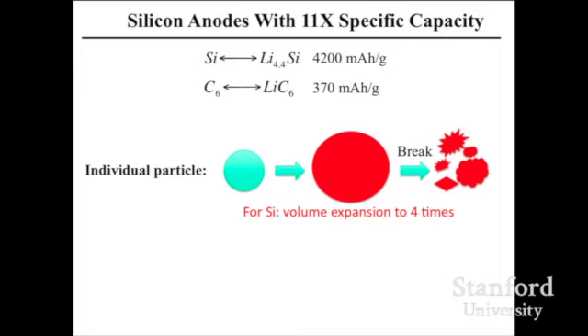This lithium comes in, breaks all the silicon-silicon bonding, and we form lithium-silicon bonding. Their volume expands very big, 400%, and then a lot of stress builds up, and they break. And this breaking is really killing the battery. The first time you charge your battery, the battery is already dead. Basically, that's the conclusion. So how do we avoid the breaking?